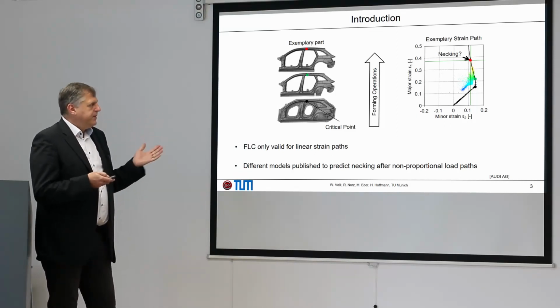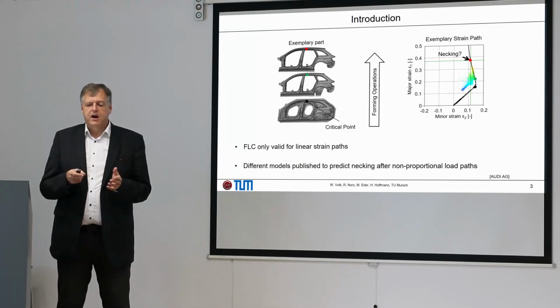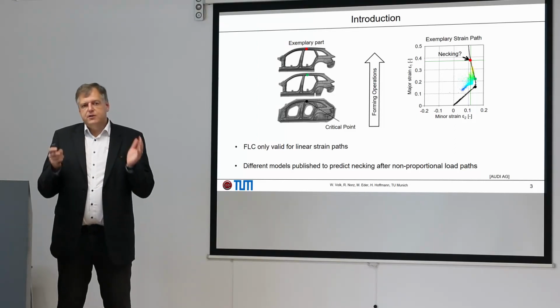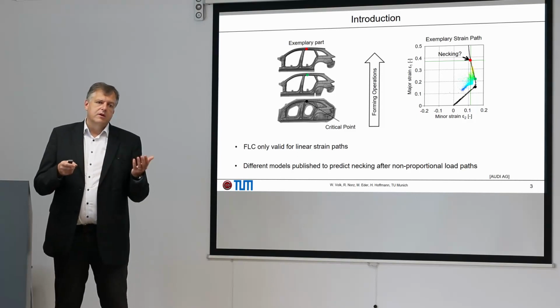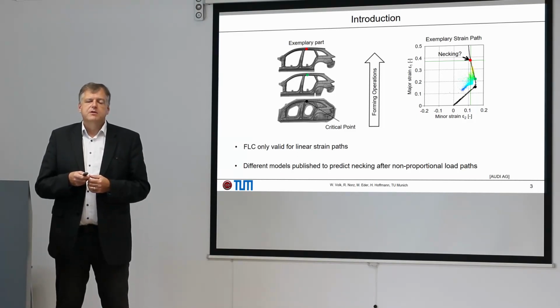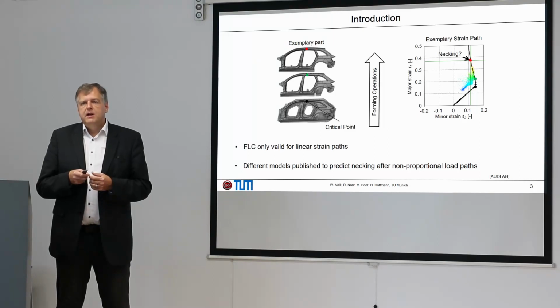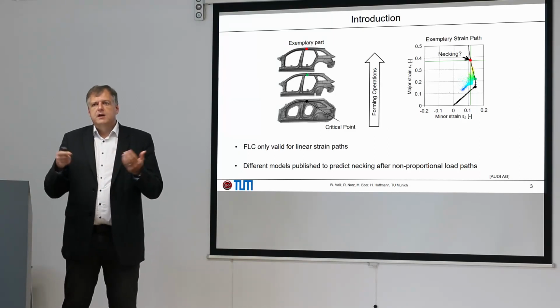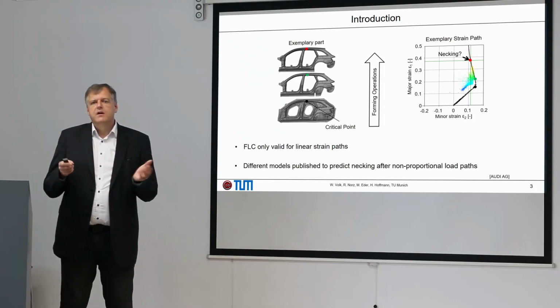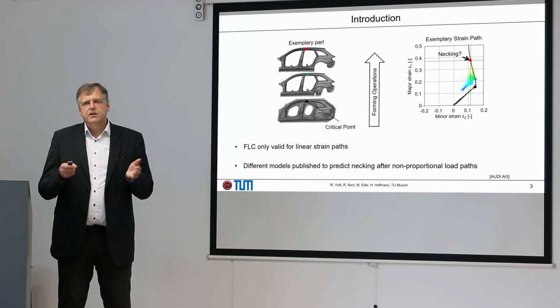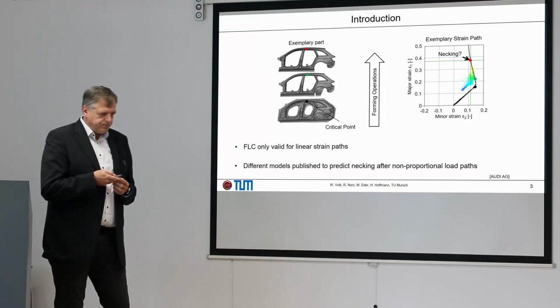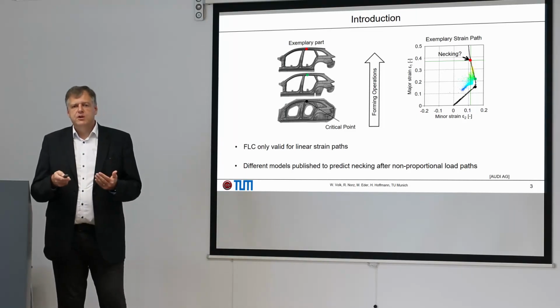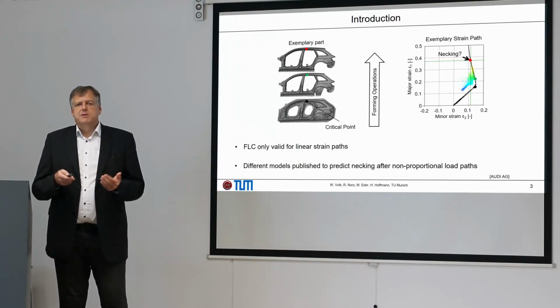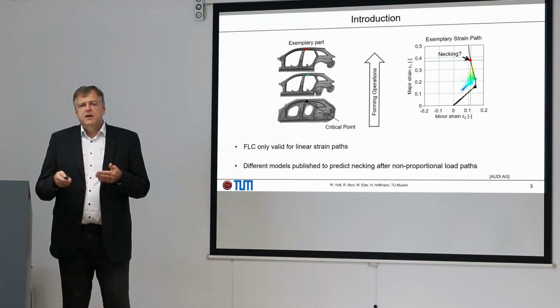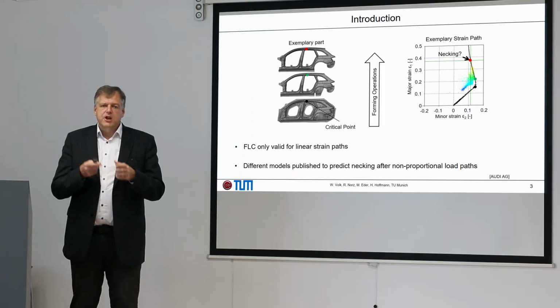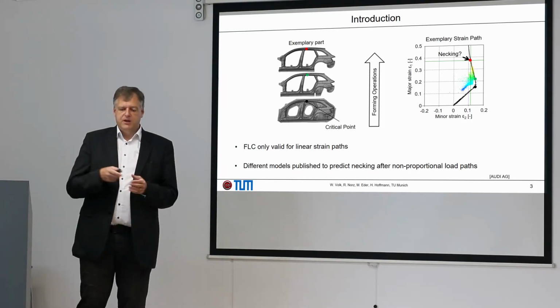So, one topic which is not taken into account so far is the question of anisotropy. We know, based on change in the substructure of the material, that we have anisotropic behavior. We know that we have different yield strength when changing the loading direction with respect to the rolling direction. So this is one of the main objectives of this work. Also to prove experimentally what happens when we have a non-proportional load path in addition with the change of the loading direction with respect to rolling direction.